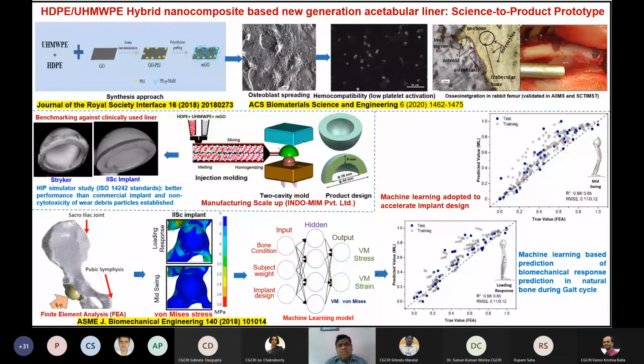So what is the strategy we have used? We have used a blend of the HDPE/UHMWPE, because if you want to add a lot of reinforcement to UHMWPE per se, it is very difficult because of the high viscosity. And we have chemically grafted this graphene oxide, then added it to the HDPE/UHMWPE blend in order to increase the strength to the level of 65 megapascal, which is quite impressive as far as the strength of this material is concerned.